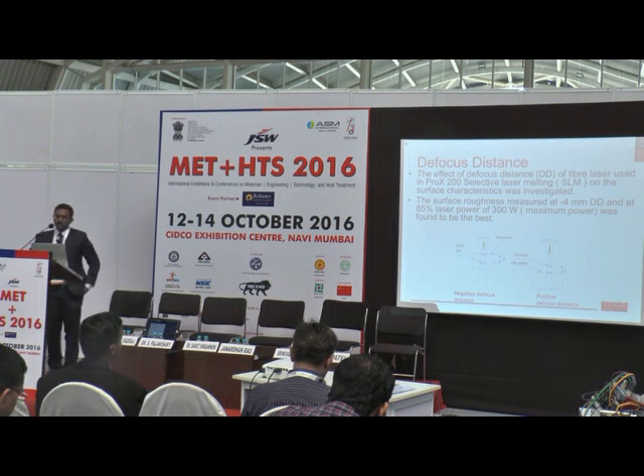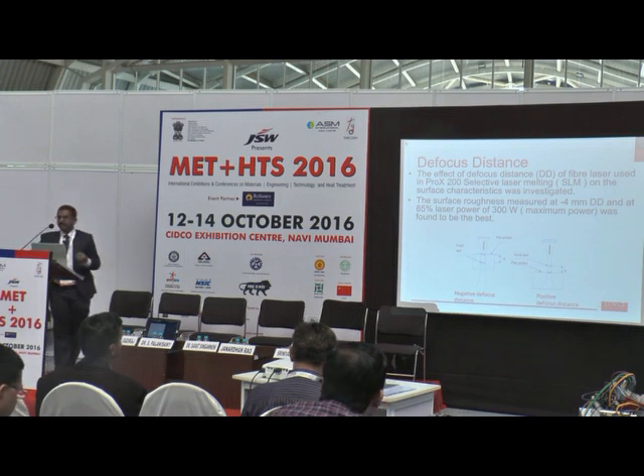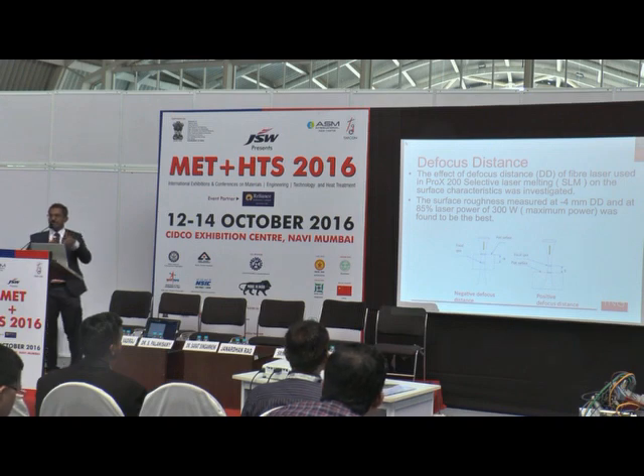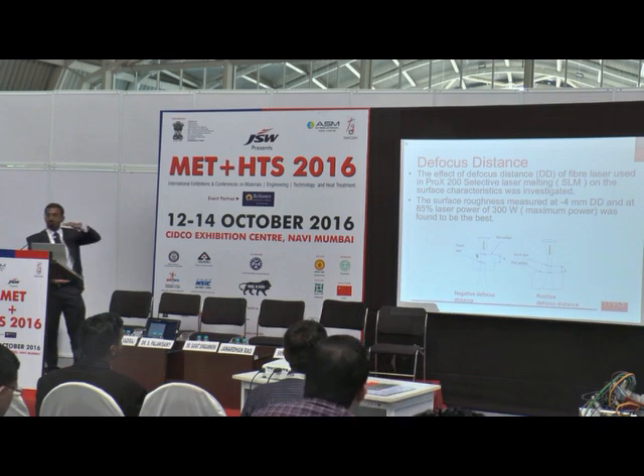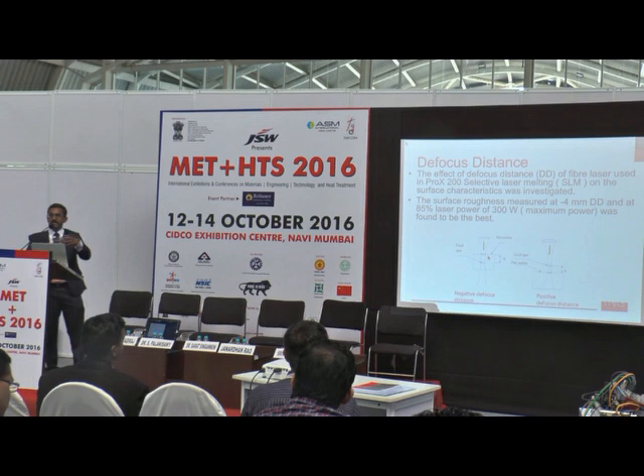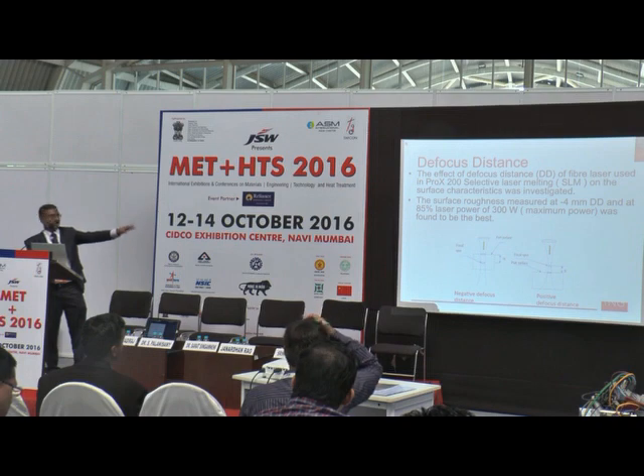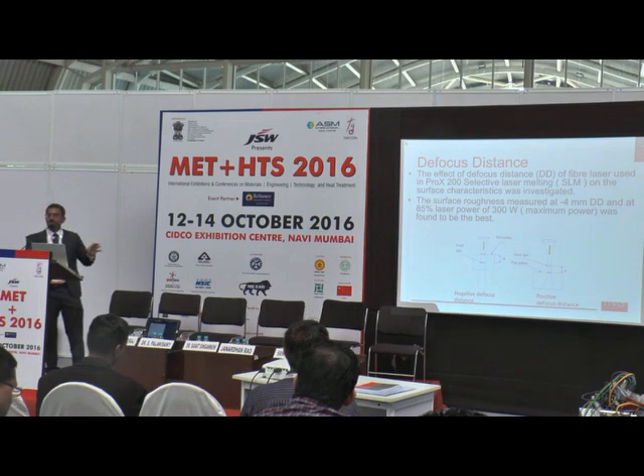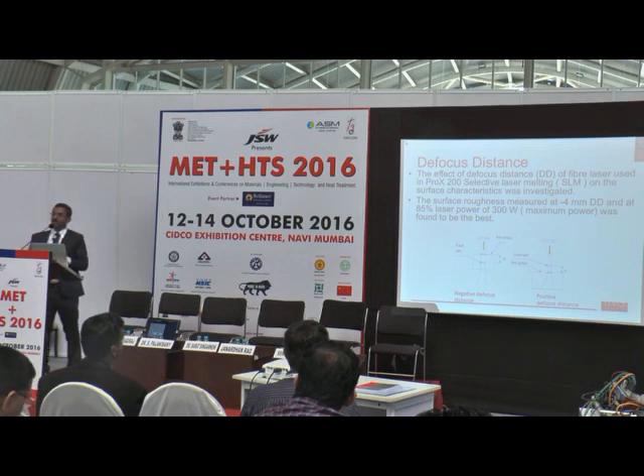Another parameter I want to talk about is the defocus distance. This is where the laser power is focused. In this particular case, the negative focus means this is the layer where the powder is, but the focal point is at -4, under the surface, because the heat intensity will be more and won't disperse after that. The other one is the positive defocal length. In our experiments, we found -4 defocal length is good. Again, this will change depending on the size of particles you're using and the average particle size.